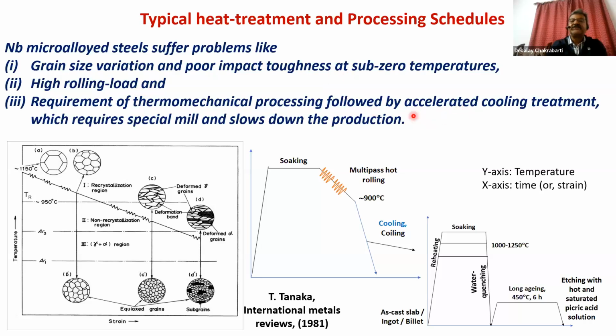And often, to restrict the grains to the fine size, these niobium steels require control rolling and accelerated cooling treatment. Installation and control of such a unit is quite expensive. So in these areas, vanadium can be very useful because it can be rolled at a relatively high temperature without the need for any control rolling. The rolling load requirement remains much lower. And if we can control the cooling path, then we can get a very fine precipitation. Vanadium precipitation is much finer and much more uniform, and we get a very fine grain structure. So in a nutshell, this is the benefit of vanadium.